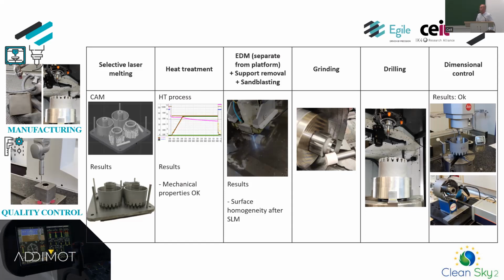After that, the heat treatment, which Miden has explained. After that, it's time to remove the built parts and supports from the platform. A curiosity of this material when applying this heat treatment is that it becomes brittle. That's why we decided to take off these extra materials using grinding and also drilling. And afterwards, the dimensional control test and CT scan in order to check that there are no cracks or micro cracks in the manufacturing of these components.